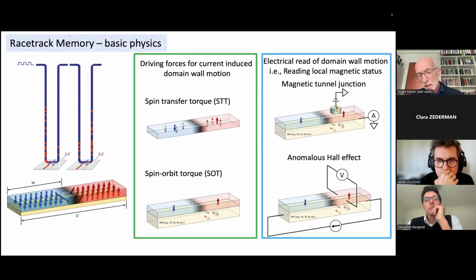That's the idea. And it turns out these spin currents you can generate this way are more efficient than the spin transfer torque. So in the case of spin transfer torque, the domain walls can be moved at speeds of 100 meters per second, we showed, and with the spin orbit torque, we demonstrated speeds of about 300 meters per second. And these are basically still what is possible today using useful materials.